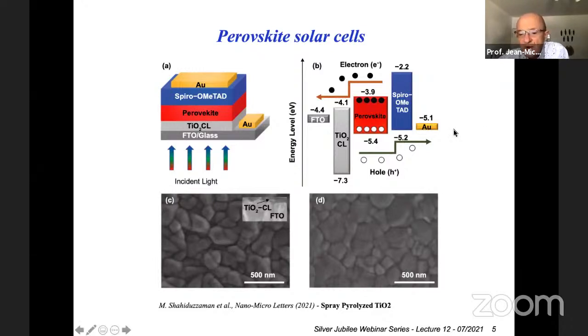So if the contacts are properly designed and are properly uniform, it's possible to grow larger crystals. So everybody is doing a lot of microscopy to explain how the crystals of the perovskite are growing, because larger crystals mean fewer defects and longer lifetime of the electron-hole pair in the material, which means a larger probability of collection of the electron-hole pair and a larger open circuit voltage for the material. So there is a lot of work, and we have been doing that work, which was published in several papers.